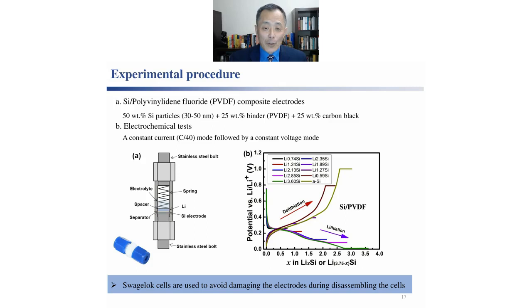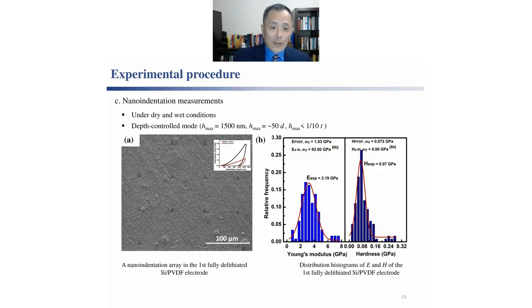We prepared our samples by electrochemically introducing lithium into the composite electrode, and then disassembling the coin cell and taking this electrode with different concentrations of lithium to the nanoindenter without exposing the sample to air. So we can measure the mechanical property of this composite electrode either under dry or wet conditions.